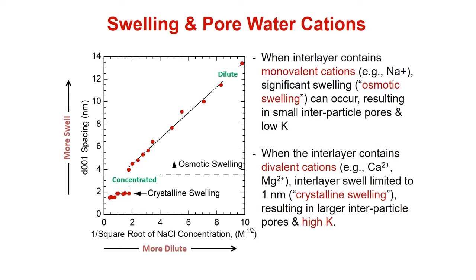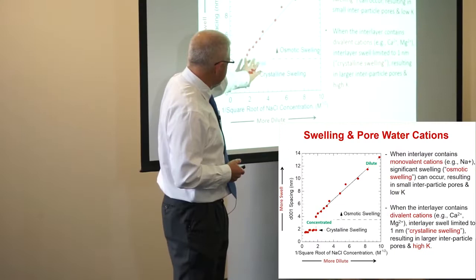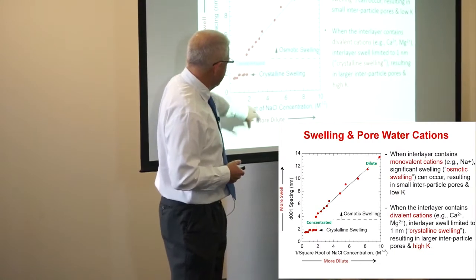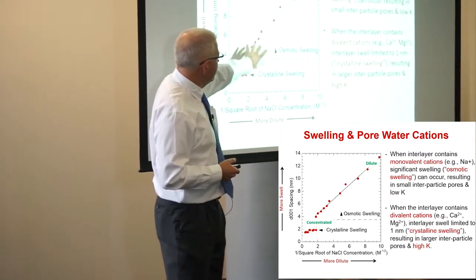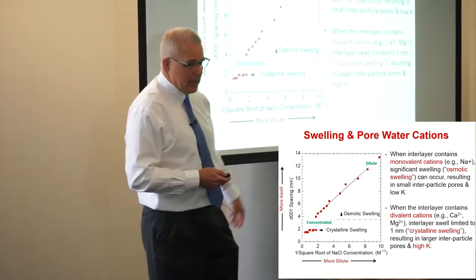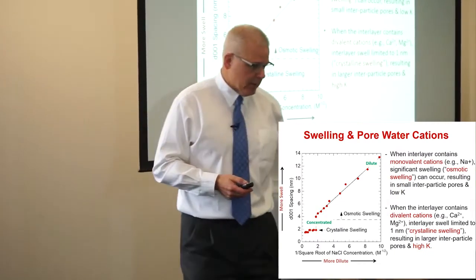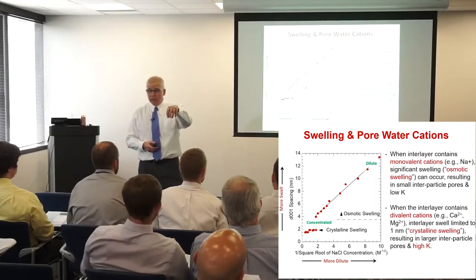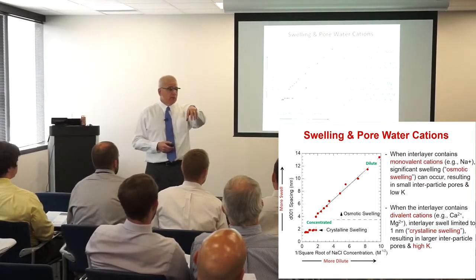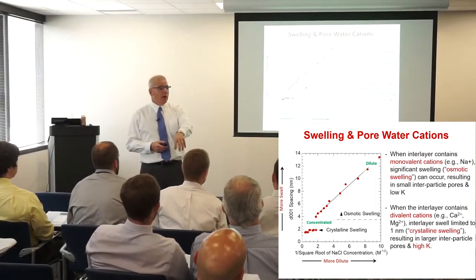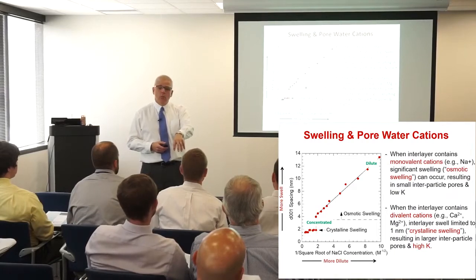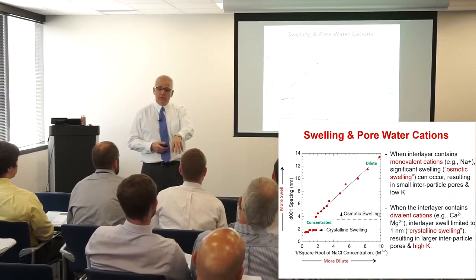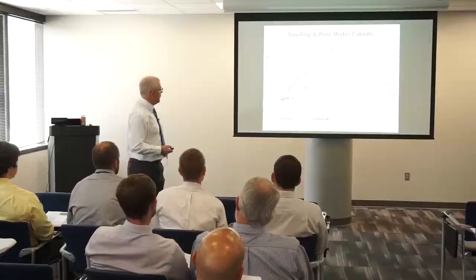This effect is related to concentration. Concentrated solutions give us only crystalline swelling; very dilute solutions give us a lot of osmotic swelling. That's one reason, for example, we put bentonite chips in a monitor well in groundwater — that's a pretty dilute solution — and they swell and seal wells really well.